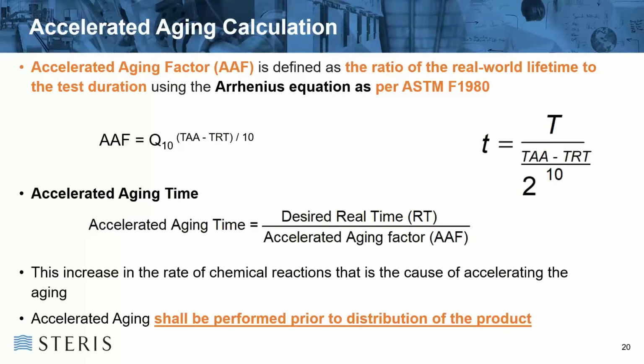You're using the Arrhenius reaction rate. So first you calculate your accelerated aging factor. And basically what that's done is 2 to the power of your accelerated aging temperature minus your real-time temperature, divided by 10. And that's then plugged into the accelerated aging formula and divided into the real time that you want to actually assess. This increase in the rate of chemical reaction is what has caused the accelerated aging,